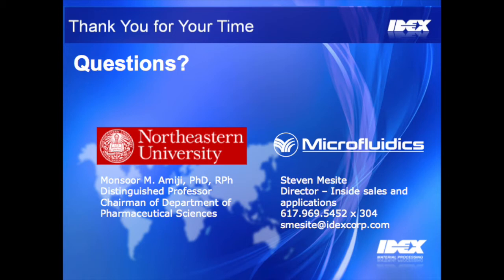So, good question again. There are several ways to characterize stability of nano-emulsion. I mentioned a couple in the discussion related to the DALDA peptide. The most common, if you're just testing stability in vitro, is the size of the droplet and changes in size of the droplet, and zeta potential values over time, which is a very easy thing to do. You just take a small volume at different time points under different conditions of storage, and then measure the size and chart changes over time. And ideally, you shouldn't see more than a very small daily variation in the size and charge.